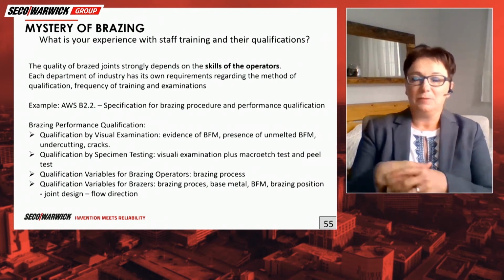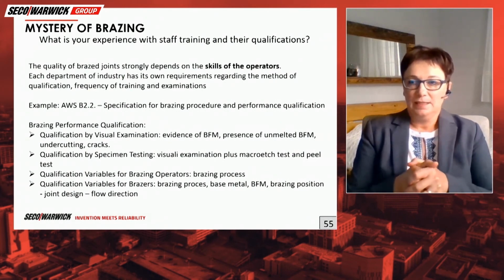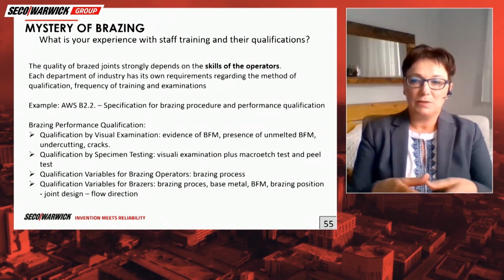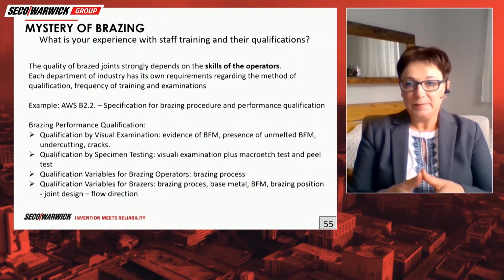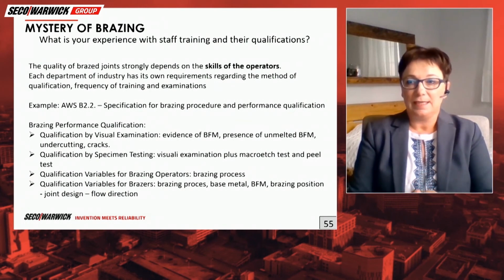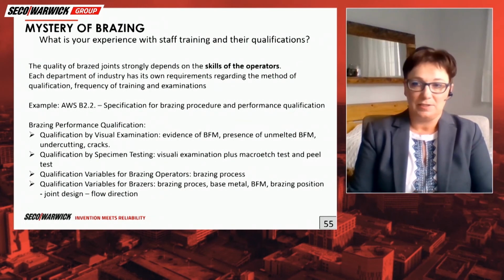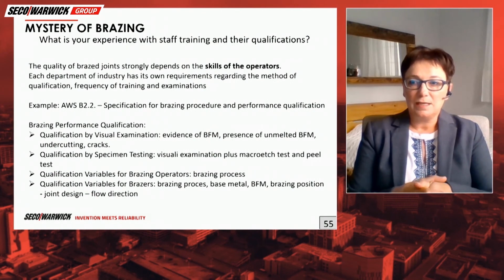Brazing performance qualification may be done in two ways. The first is similar, as Adam said, visual examination. So we have to check evidence of brazing filler metal, brazing line, presence of unmelted brazing filler metal, undercutting, cracks, erosion, etc. The second, more detailed, is qualification by specimen testing. So visual examination plus macro test of the samples and peel test.